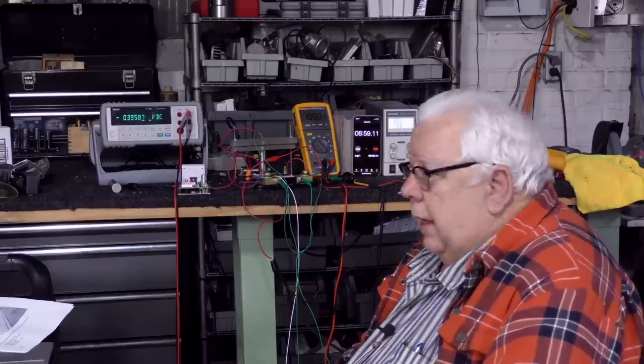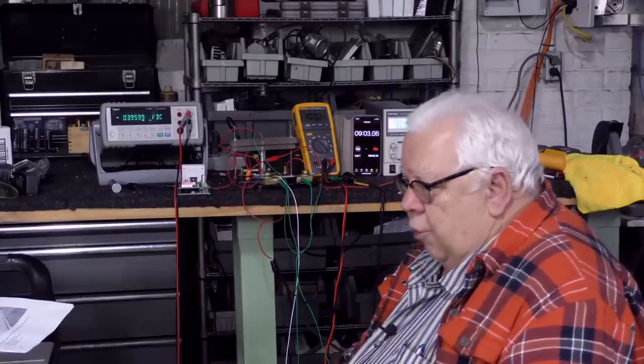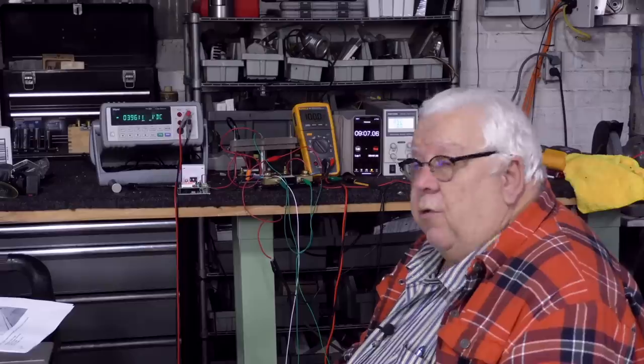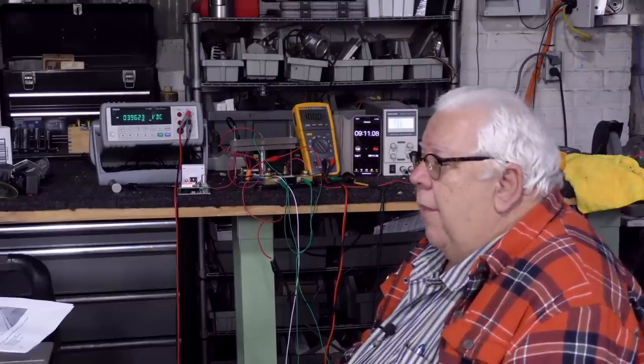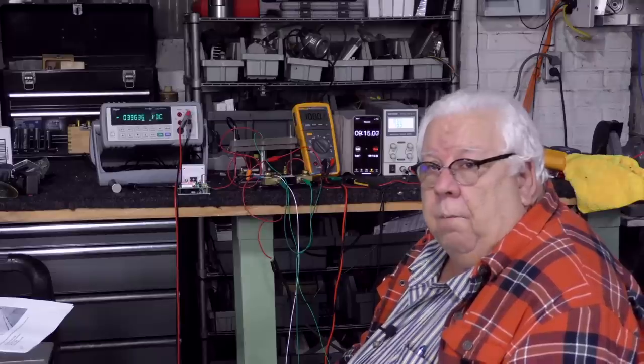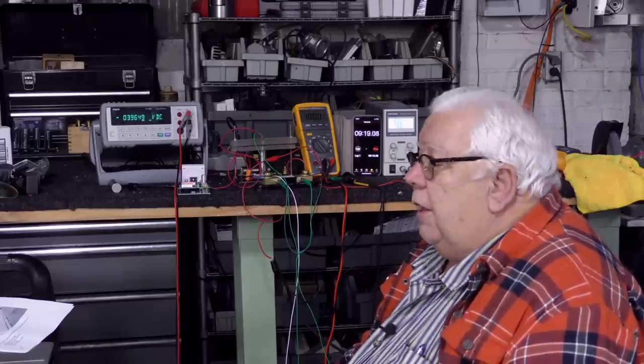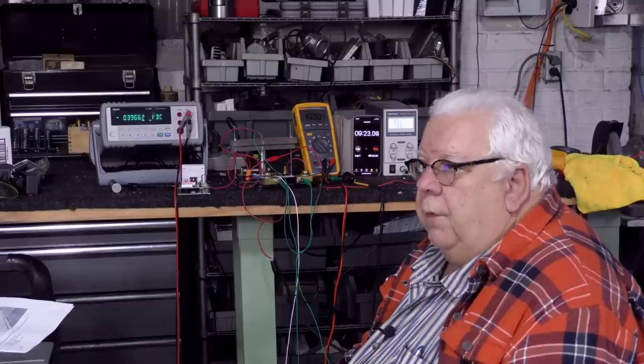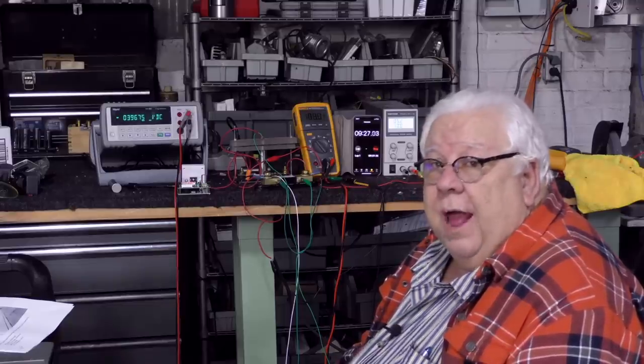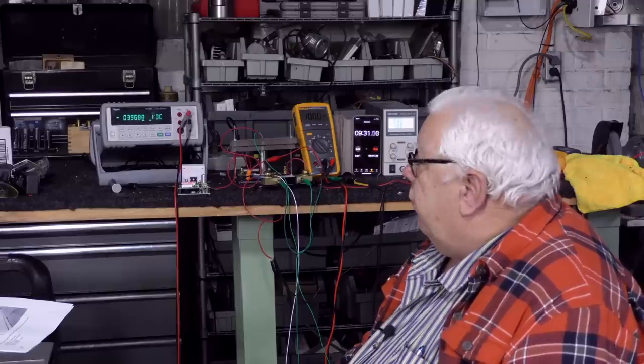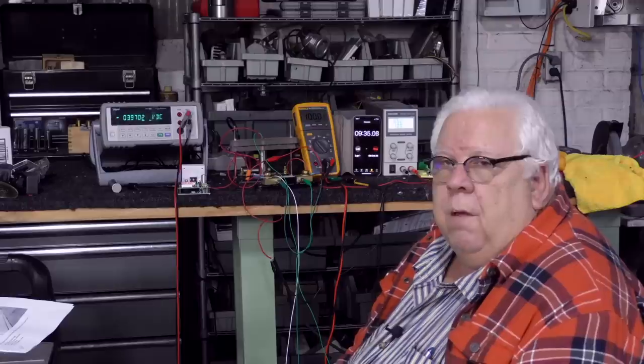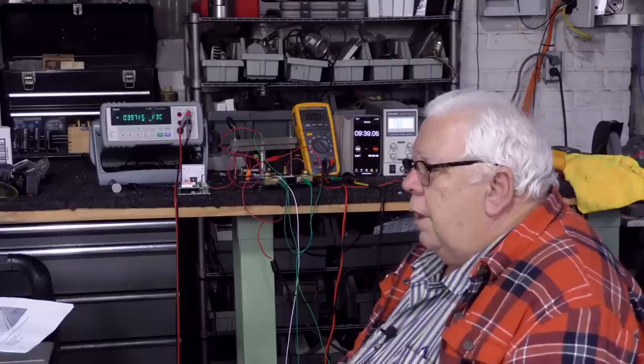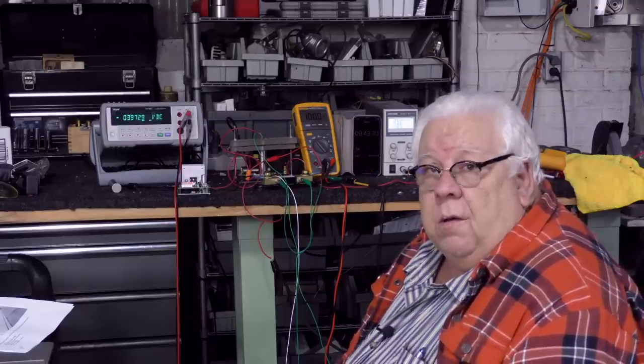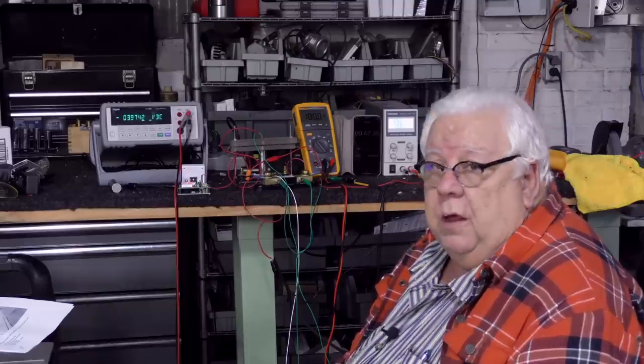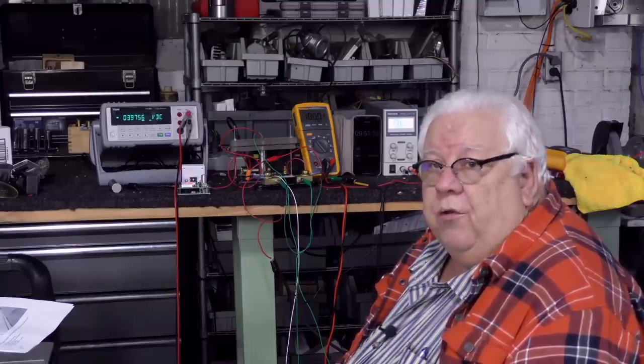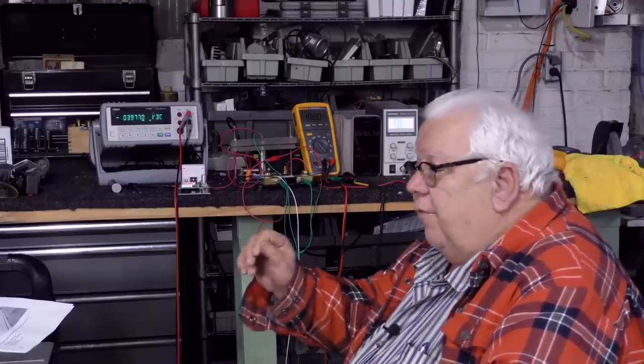A123, a number of years ago, this came out of MIT, came up with a new incremental advance in lithium iron phosphate chemistry, and they came up with a very finely ground, much smaller particle size for the active materials. The addition of a carbon, a very fine graphite additive to the cathode side, and they used a process to make an extremely thin layer of material on the cathode. This let them do 20C discharges. These batteries might be good for 3C. But the A123 batteries would routinely do 20C, having this very thin layer.